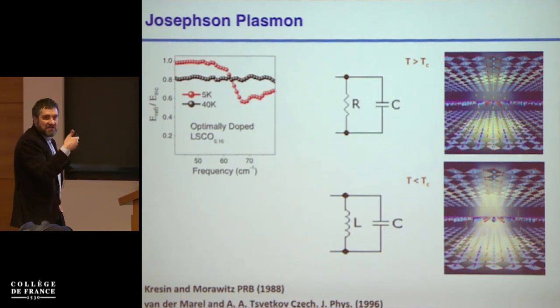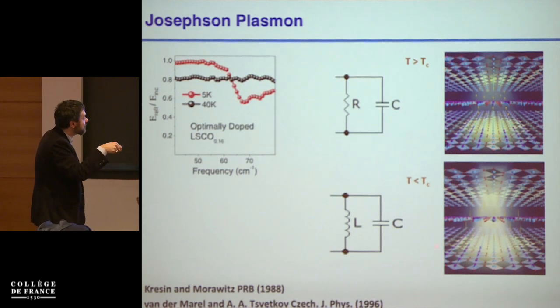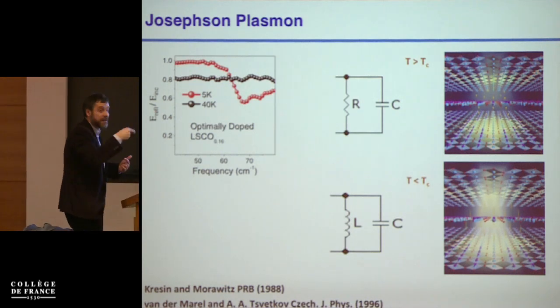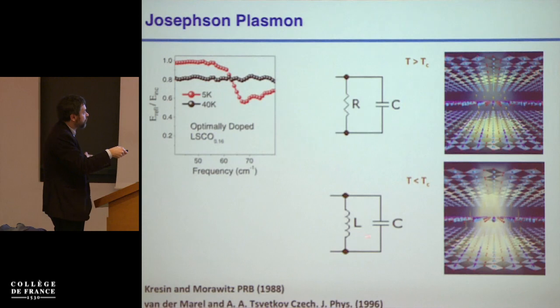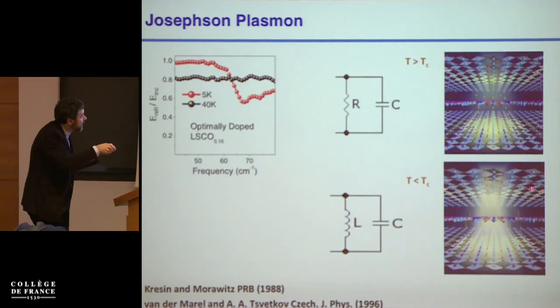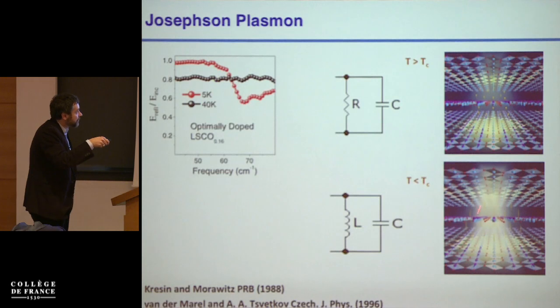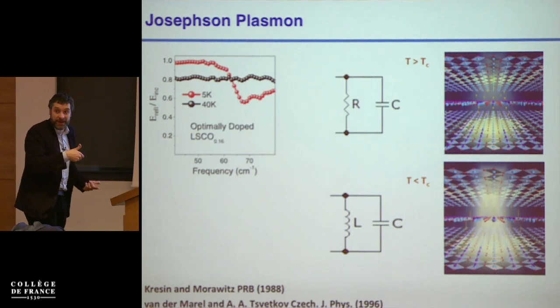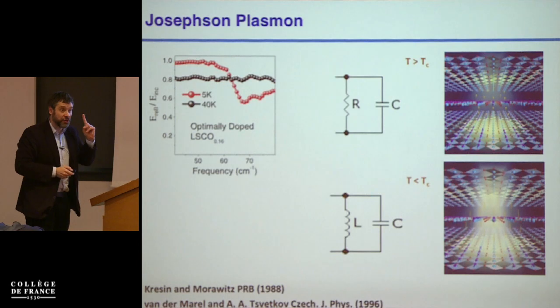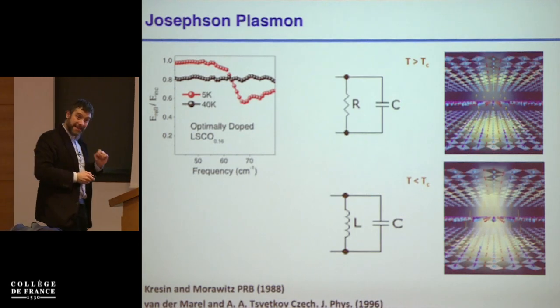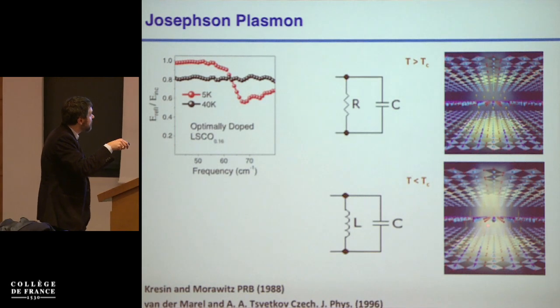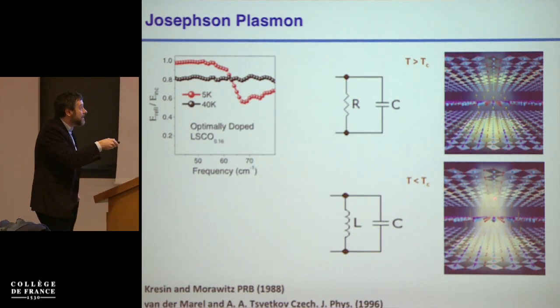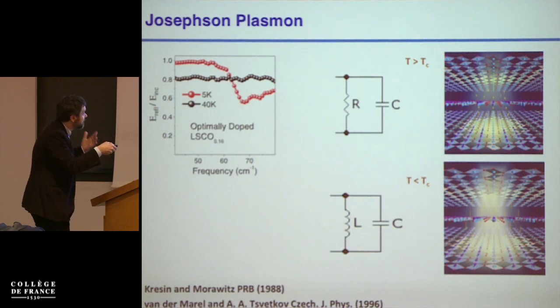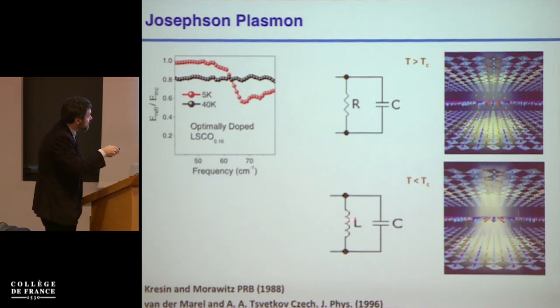Okay, so to zero order, I can think of the electrodynamics of these cuprates perpendicular to the planes as some LC type coupling, which has a very clear resonance, which is at 1 over square root of LC, and this gives rise to oscillatory tunneling of Cooper pairs between these capacitively coupled planes. Okay, so if I now measure, I will find a very specific resonance in these cuprates at one specific frequency, which is related to the capacitance of the planes, is a number of things, but everything else being equal, the exact frequency at which I find this is related to the density of Cooper pairs in the planes.